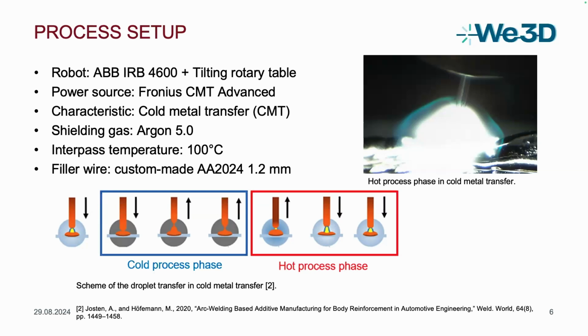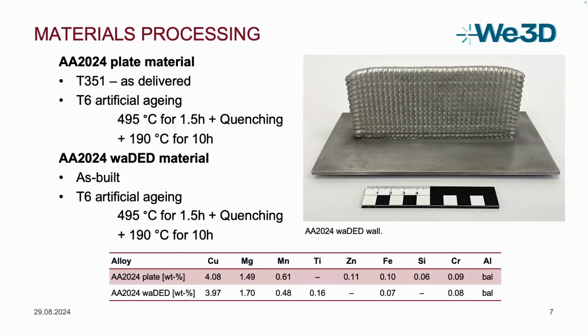As mentioned, we used cold metal transfer as a process, and basically we have two process phases for this cold metal transfer: a hot process where the arc is burning and the wire is melting, and a cold process where we have no arc and the droplet transfer is assisted by a wire movement. And because we have this cold process phase in CMT, we reduce the heat input and can reduce the heat accumulation in the previous layer, and therefore CMT is quite often used for additive manufacturing procedures.